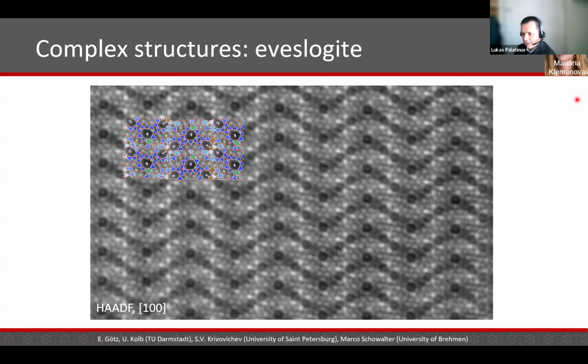It is again just like for X-ray diffraction. Of course, it's better to have a single crystal if you have overlap of domains, either by twinning or by random orientation. There are complications of overlapping intensities that need to be handled, but all this is not different between X-rays and electrons. So in principle, it is possible to deal with such crystals. But as I said, the best results are obtained from the best crystals, and one of the features of a good crystal is that it is alone in the beam. So that's of course always preferred.